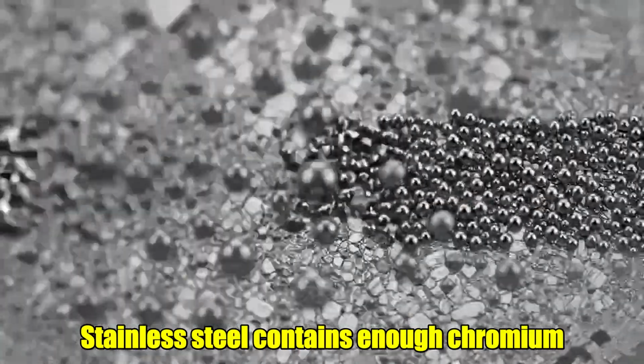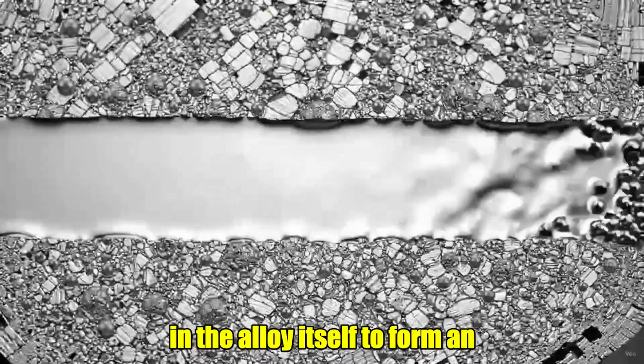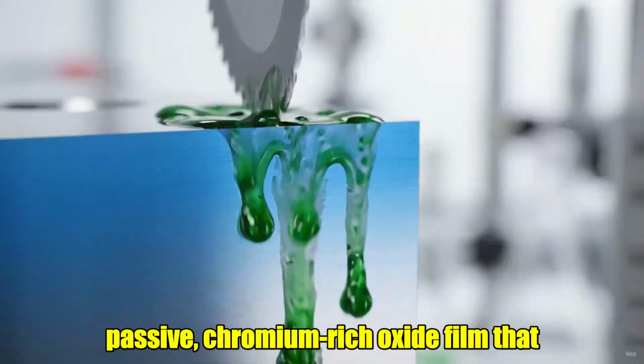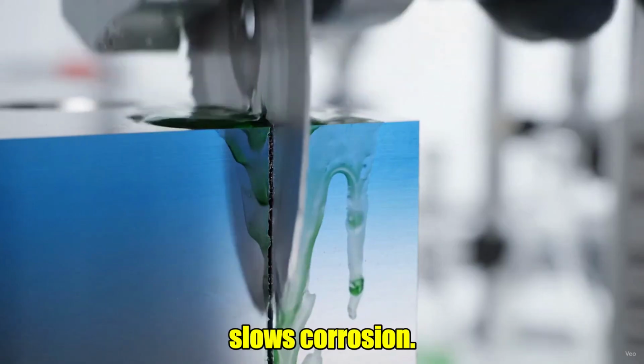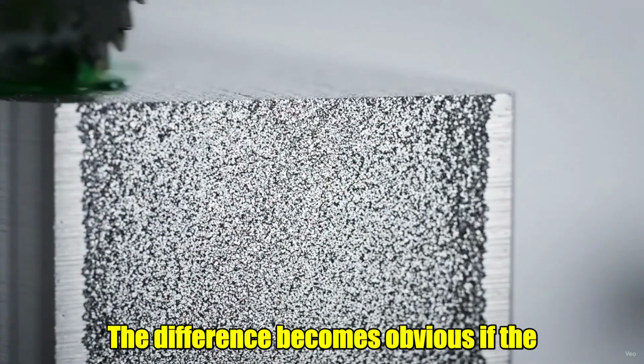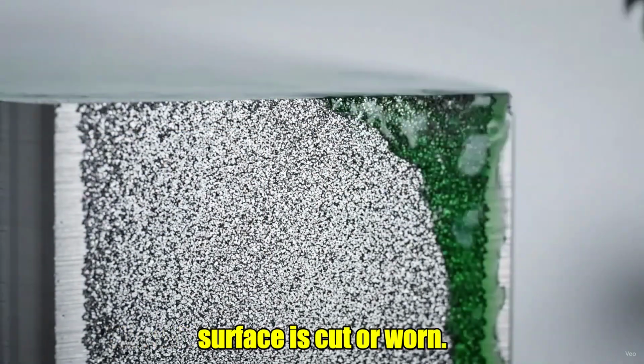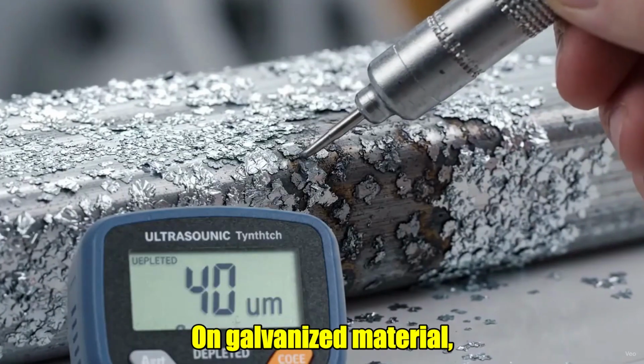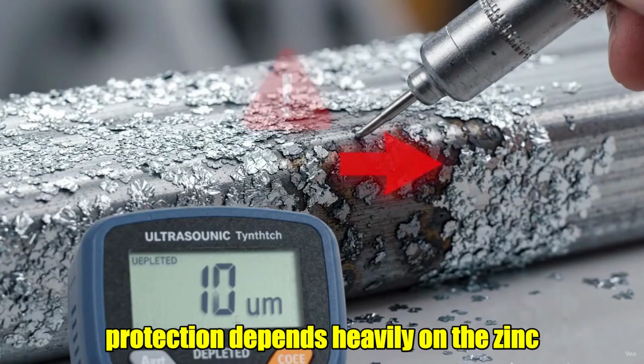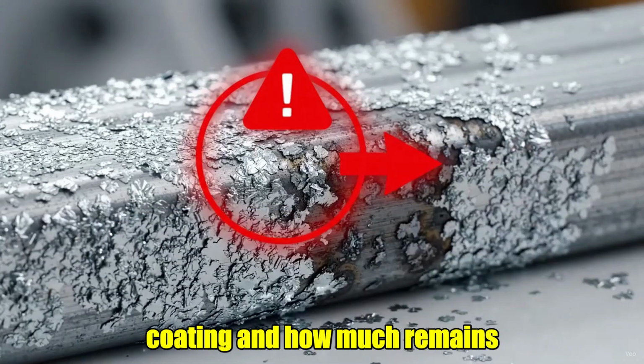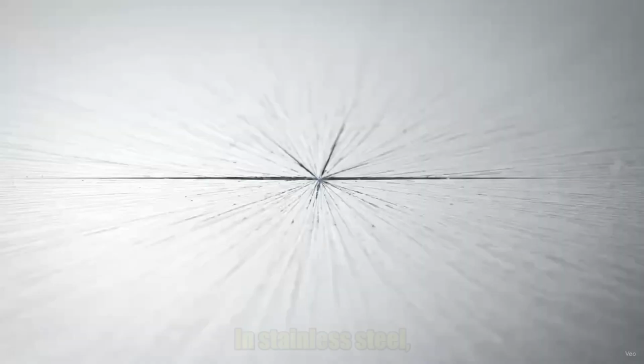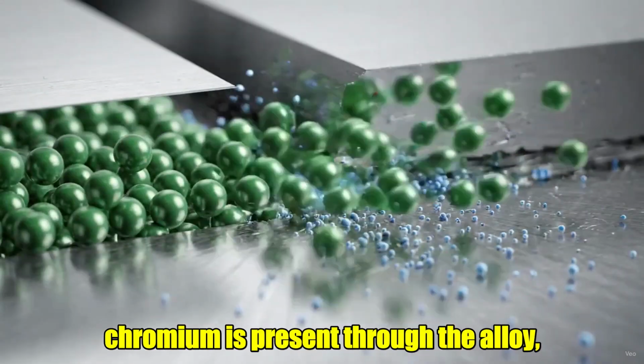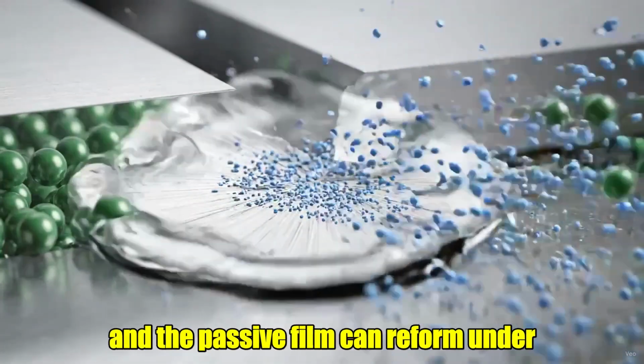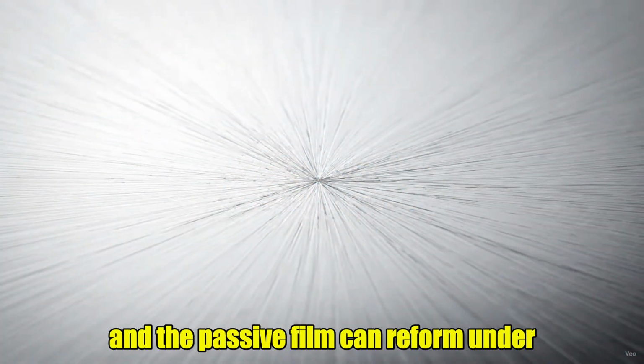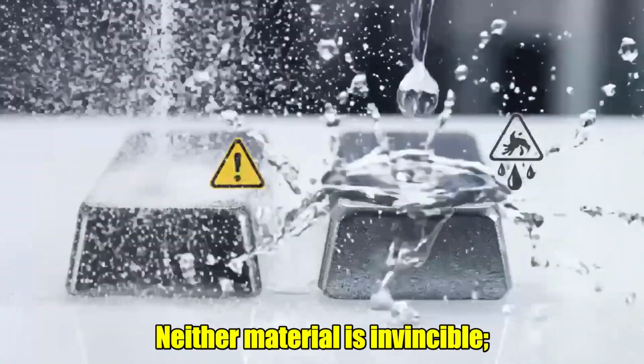Stainless steel contains enough chromium in the alloy itself to form an extremely thin, passive, chromium-rich oxide film that slows corrosion. The difference becomes obvious if the surface is cut or worn. On galvanized material, protection depends heavily on the zinc coating and how much remains around the exposed area. In stainless steel, chromium is present through the alloy, and the passive film can reform under suitable conditions.